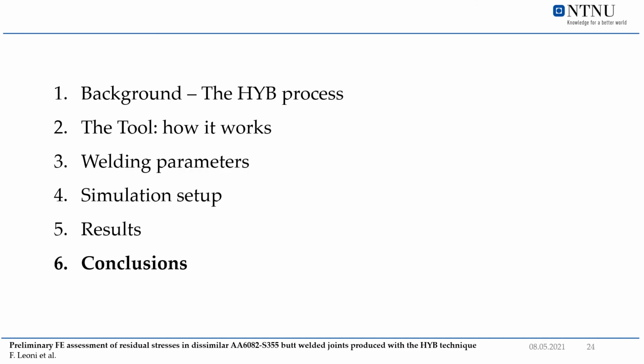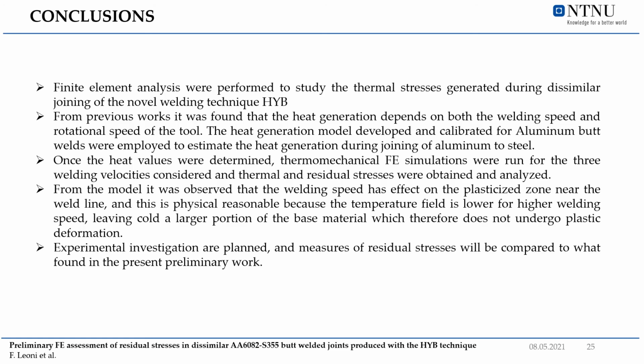And now let's finally draw some conclusions. Finite element analyses were performed to study the thermal stresses generated during the dissimilar joining of the novel welding technique HYB. From previous works, it was found that heat generation depends on both the welding speed and the rotational speed of the tool. The heat generation model developed and calibrated for aluminum butt welds was employed to estimate the heat generation during joining of aluminum to steel.